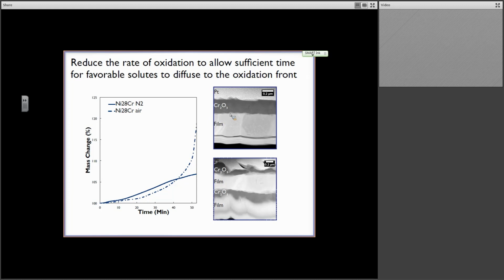If I take the exact same film and do the exact same experiment now in air, I also form a chromium oxide scale on my thin film, which is now right here in the middle. And this dark region is oxide in both cases; you can ignore the contrast at the bottom here. That's just an artifact of the sample preparation. But now the mass gain is huge, though it doesn't actually look like there's as much oxide here because it has this spiky-like morphology, which means it's more prone to fall off or delaminate with time. So it's mechanically compromised, and because of the spiky morphology, it's less dense. There are easy access pathways to the surface, okay?